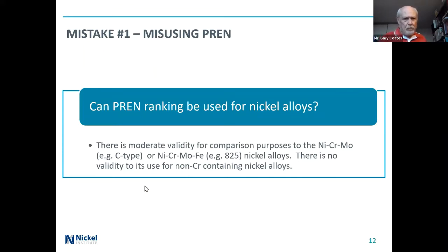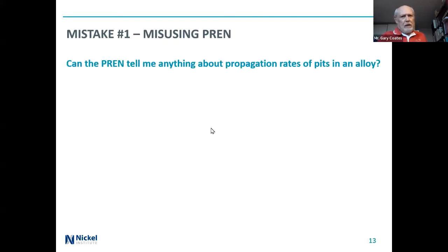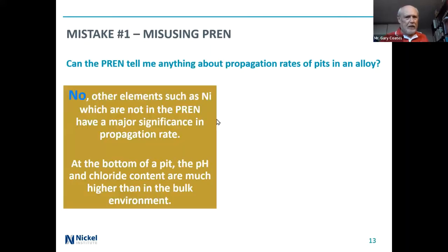Can PREN numbers tell me anything about the propagation rates of pits in an alloy? And again, the answer is no. Other elements such as nickel, which are not in the PREN, have a major significance in reducing the propagation rate. And you have to remember at the bottom of a pit, the pH and the chloride content are much higher than in the bulk environment. And so therefore it's a very different condition. And PREN is measured on the initiation to pitting, not the propagation of pitting.